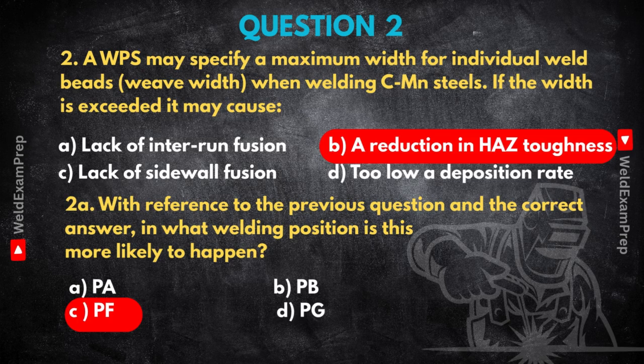Okay, so that wraps up this focused deep dive into some pretty critical CSWIP 3.1 concepts. Just to recap quickly. We saw why that X2 to X5 magnification is the sweet spot for visual inspection, especially for nailing things like undercut. Then we dug into how exceeding the specified weave width, particularly in CMN steels, isn't just messy, it can seriously reduce HAZ toughness because of that extra heat input causing coarser grains. And we learned that this risk, well, it's significantly higher when welding vertical up, the PF position, because of the techniques often needed to fight gravity.